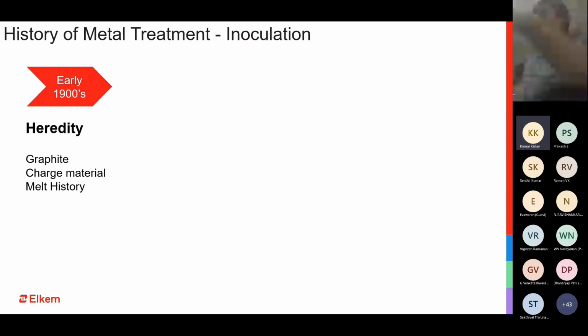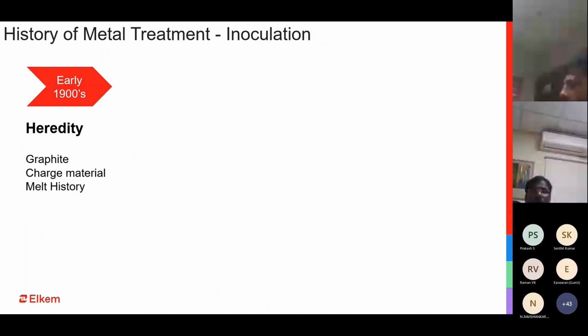But what was happening in the 1900s or so, we had the liquid metal which had some inherent hereditary particles within the metal, which was giving it the inoculating effect, giving it the site for the growth, for the solidification, for the phase change. What was it? Most of it was the graphite. Graphite still today is considered one of the very strong graphitizers. It gives you a lot of carbon conversion to graphite, which eventually becomes flakes or nodules or whatever. So graphite, the charged material, use of pig iron, use of charged metals which are rich in nucleating potential, and of course the history of the melt. I mean, the heat, the temperature, the time, etc. So that was the core essence of inoculation as a concept back in the 1900s.